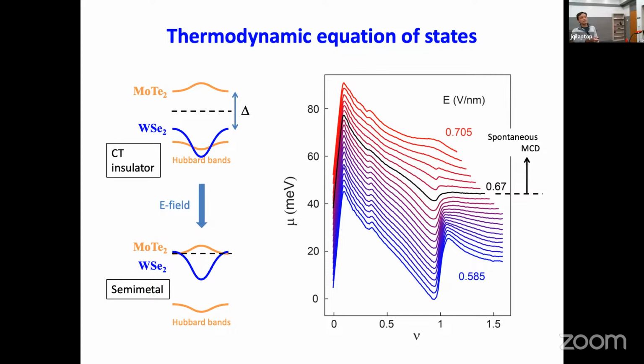A few things I want to note: there is this black dashed line around this electric field. When you push up the electric field further, there's a spontaneous magnetic circular dichroism signal coming out from the sample that signifies time reversal symmetry breaking, and that's where we get the Chern insulating states. So above this electric field, we get a Chern insulating state, and as we push the electric field further, we close the gap. Also, I would like to note that the chemical potential keeps dropping with increasing density. That means a negative compressibility in the sample. It's very typically seen in all these Moiré systems that the net compressibility is negative.